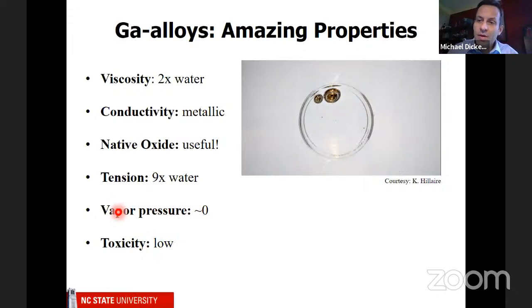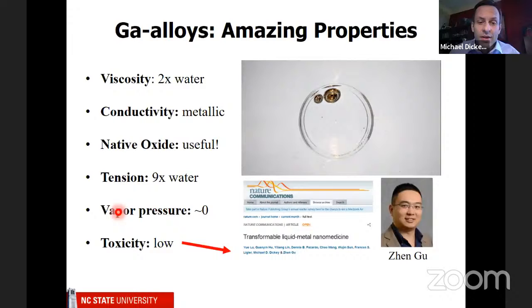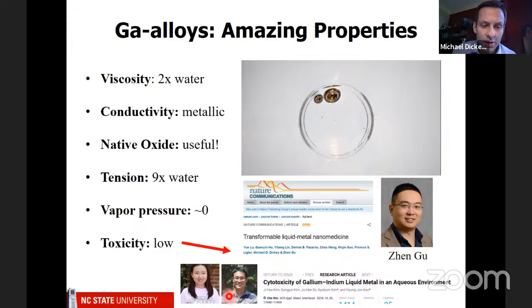And people always say, well, it's a liquid metal, so it's probably got high toxicity. And actually, no, it does not. Mercury is toxic, but not gallium. One of my colleagues came up with this idea of using liquid metal for medicine. I thought that was a little bit crazy, but it turned out to be a good idea. This is my former student and her husband, and they actually studied the toxicity of gallium and found it to not be toxic. So we still treat it very carefully, but it suggests that the toxicity is low. Now, gallium is not found in the body naturally, so it still should be something you handle with care.